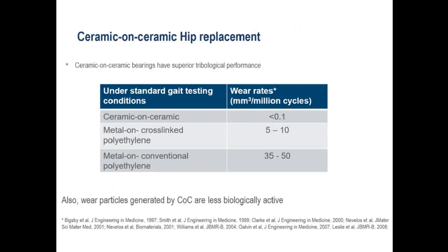Ceramic is also used as a ceramic on ceramic bearing, as a hard on hard bearing, and usually shows a superior tribological performance. Ceramic on ceramic under a standard walking cycle produces wear rates lower than 0.1 cubic millimeters per million cycles, compared to 5 to 10 for cross-linked polyethylene and also 35 to 50 cubic millimeters in metal on conventional polyethylene material. In addition, the wear particles generated by ceramic on ceramic bearings are usually less biologically active because there is a significantly lower amount of these particles released by these joints.